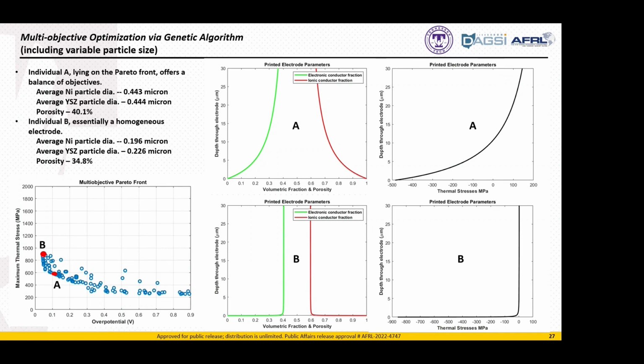We do think that once we start studying electrodes with material properties that are more similar, here we have a nickel and a YSZ where one is just an electronic conductor and the other is solely an ionic conductor. If we have mixed conduction in some of the materials, then we expect that gradation might improve the cell performance by a little bit more. But this is good for us to validate these things through theory before we really begin printing.